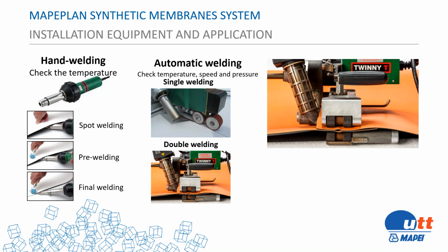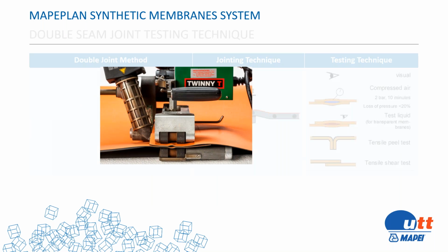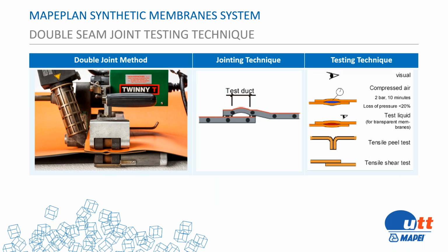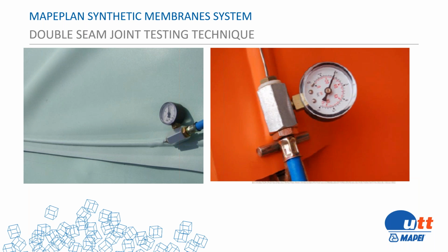Most of the time, the standard asks for a double welding overlap. Double welding overlap means we have two seams, one on the right and one on the left, and in between we have an air channel, an open channel, that we use for testing purposes. After welding the overlap, we can test the joint using an air pressure test. If we close the beginning and end of the line, we will have a closed channel. We can introduce the air pressure needle.